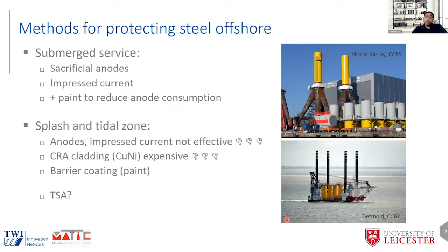So in terms of the protection system, I said we use quite a lot of sacrificial anode or impressed current type CP systems for submerged zone. And we use paint as well, or a dielectric layer, to reduce anode consumption or the current drain from the anodes. In the splash and tidal zones, these systems, they don't tend to be very effective because you don't have a constant layer of electrolyte present in those regions.